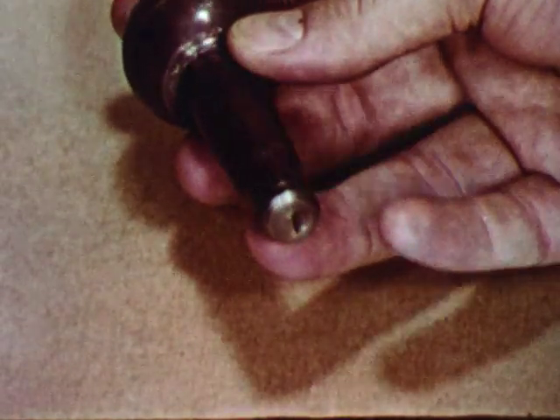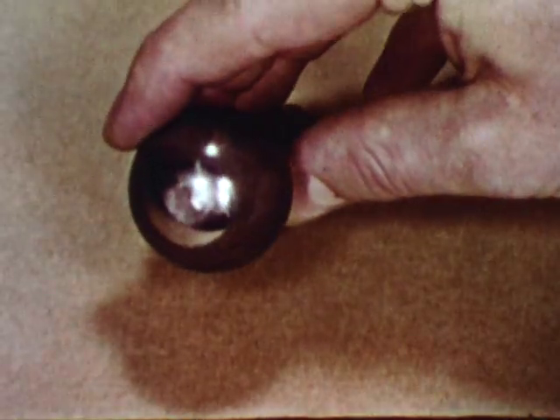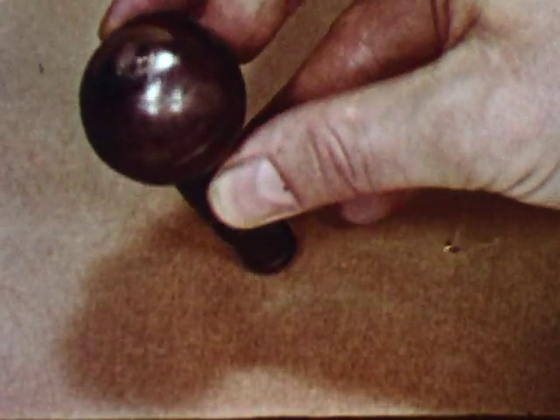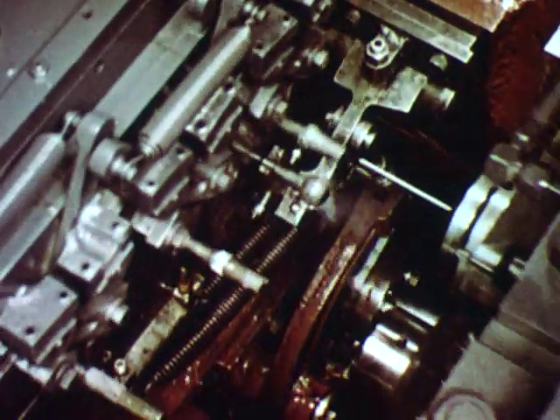This steering knuckle ball stud is produced on a 3/4 3-die bolt maker from 8640 steel wire at 50 studs per minute. You need 3 dies to gather stock and form the part. In the last punch, the long pin supports the heavy ball until the picker is in control of the blank. The picker transfers the part from the final station to the pointer tube entrance. A timed air blast blows the part up the pointer tube. The parts leave the machine after pointing. The end is threaded after a grinding operation.